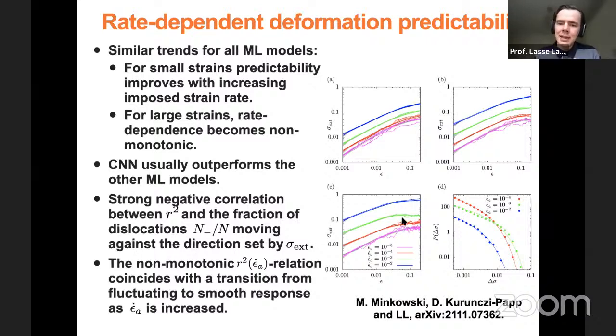And the point is that there's a transition point where you typically have only of the order of one such stress drop in your stress-strain curve, but this individual stress drop is hard to predict, because it's basically one avalanche. So the stress-strain curve is affected a lot by this individual event, which then shows up as a minimum of predictability around the onset of this transition from fluctuating to smooth behavior. I don't know if it makes sense, but I think this more or less works like that.